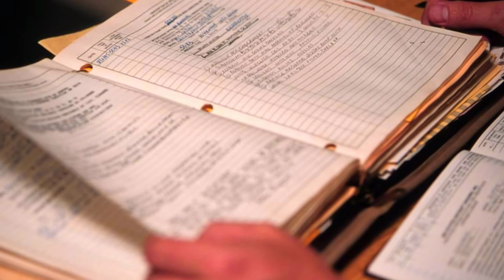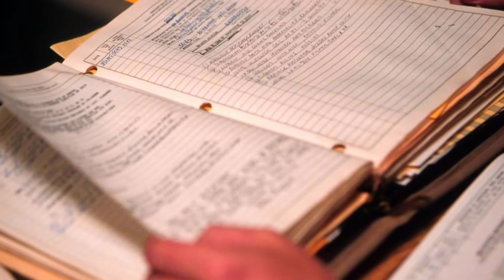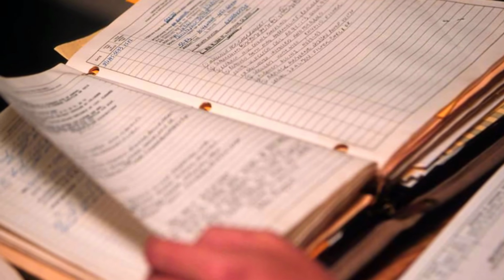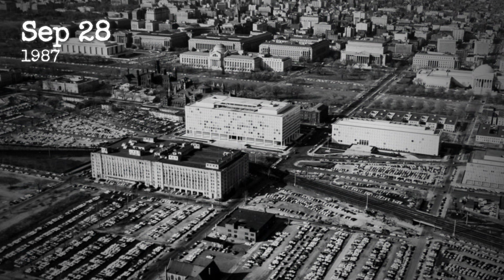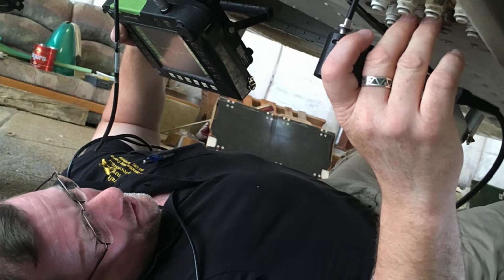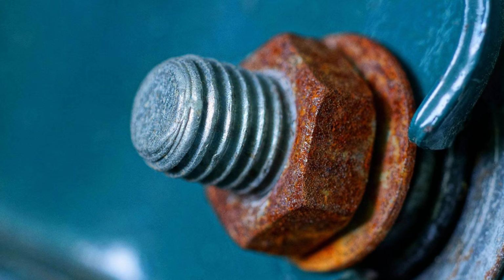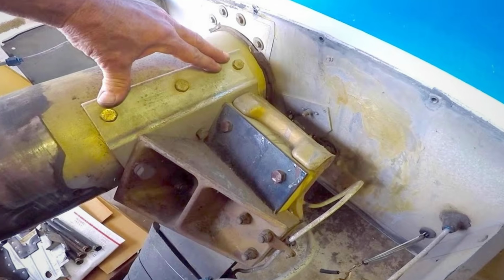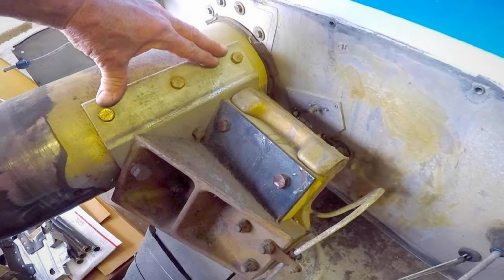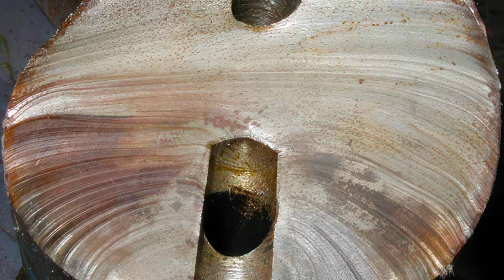He filed malfunction and defect reports to the FAA, over 40 of them. On September 28, 1987, 5 months after the Airworthiness Directive was issued, the FAA rescinded it. The stated reason was that the inspection process itself was causing damage to the bolt holes. Probing the area susceptible to fatigue was initiating new fatigue cracks.